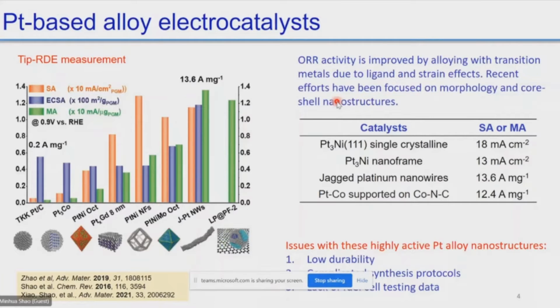But if you can control the morphology and other nanostructure, we can find that the mass activity, that's the red, the green column, can be enhanced by almost 70 times. So this is the platinum nanowire, and this is the platinum nickel molybdenum octahedron. So basically all are one-to-one phases. You can see that the activity can be enhanced significantly.